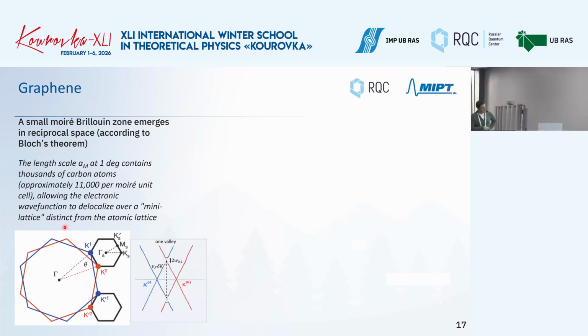So here are the blue and red. You see, when you twist one on top of the other, this K point moves to another place, and then they form this so-called mini band. If you make the cut like this from K1 to K2, you can obtain this image. There is one cone, linear dispersion, as we discussed in the monolayer regime, and another cone nearby. They see each other, and there is this overlap here.